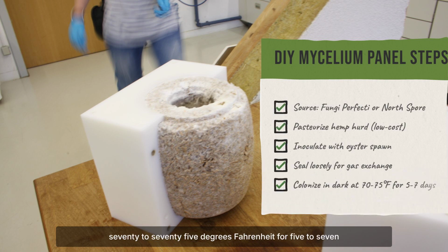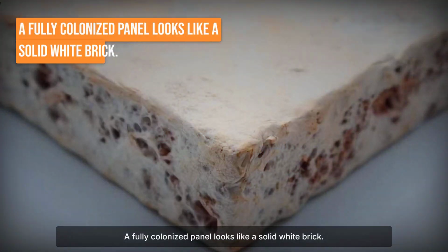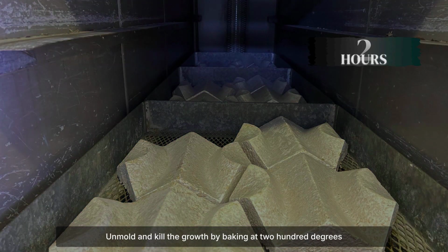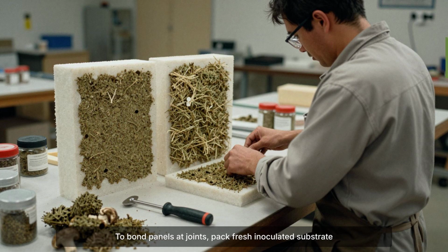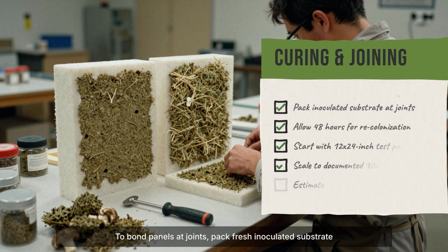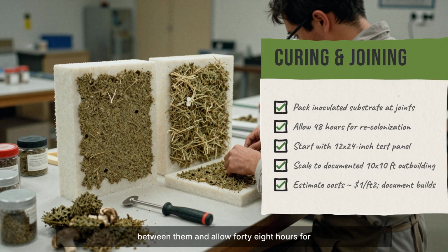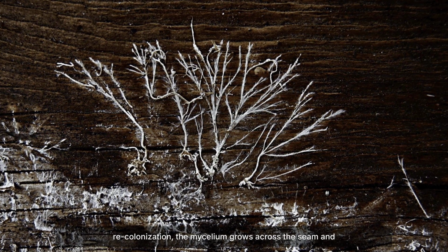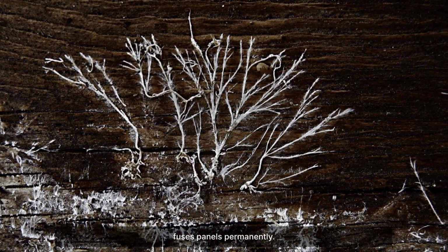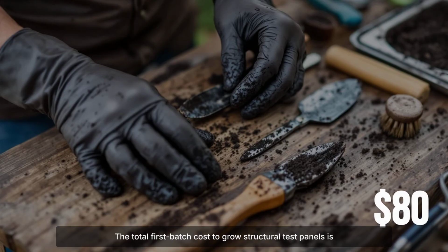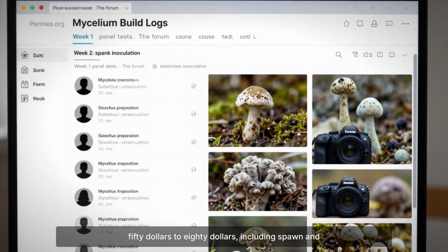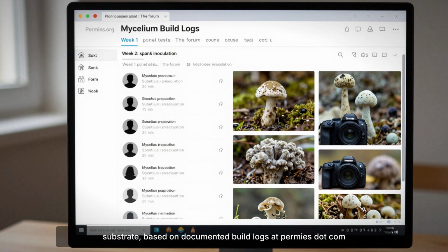Colonize in the dark at 70 to 75 degrees Fahrenheit for 5 to 7 days. A fully colonized panel looks like a solid white brick. Unmold and kill the growth by baking at 200 degrees Fahrenheit for 2 hours. To bond panels at joints, pack fresh inoculated substrate between them and allow 48 hours for recolonization. The Mycelium grows across the seam and fuses panels permanently. The total first batch cost to grow structural test panels is $50 to $80, including spawn and substrate, based on documented build logs at Permies.com and the Mycelium Underground Forum.